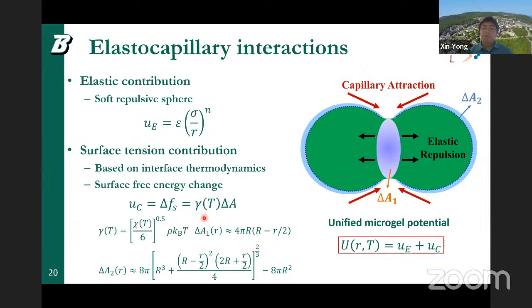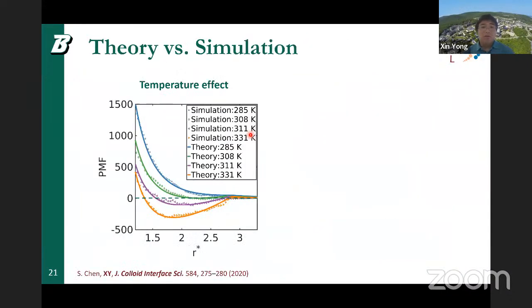And so we theoretically derive this. The surface tension also depends on the temperature, so we put our previously developed chi parameter for these hydrogels into the model. The two fitting parameters are only this n, for describing the soft repulsion, and this epsilon, which is the strength of the soft repulsion. As we can see here, the theory fits very well to the simulation data, and so we also capture this dependence on temperature.